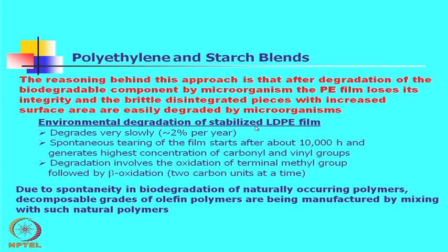Now, there are some LDPE films which are used today for packaging. These are stabilized with some stabilizers, antioxidants, etc., and degrade at a very slow rate, say 2% per year, and spontaneous tearing of such film occurs after 10,000 hours of compost or degradation. Then degradation involves the oxidation of terminal methyl group followed by beta oxidation. This is the mechanism of degradation of how this stabilized LDPE film degrades, but that is a very slow process, and we cannot consider such stabilized films as degradable polymers.